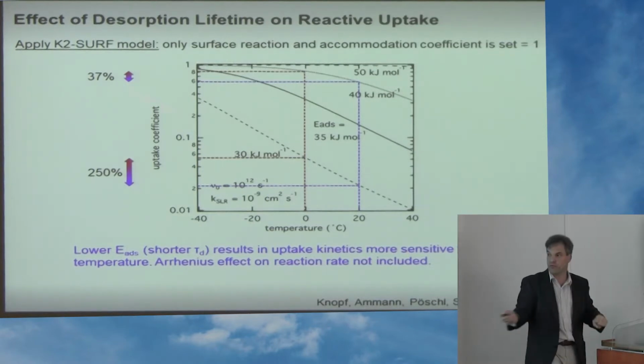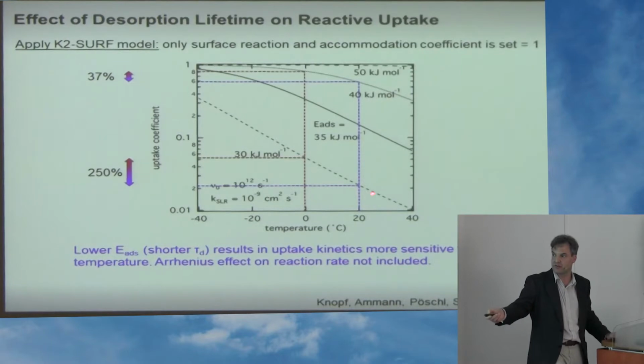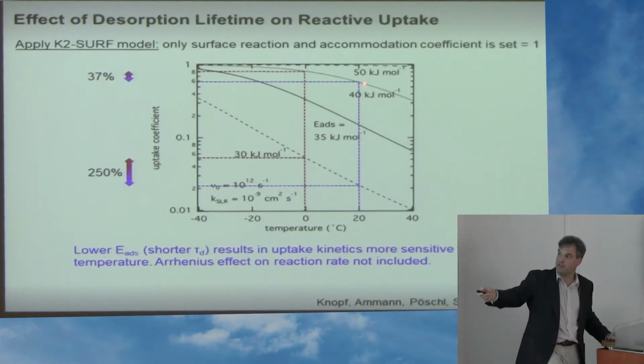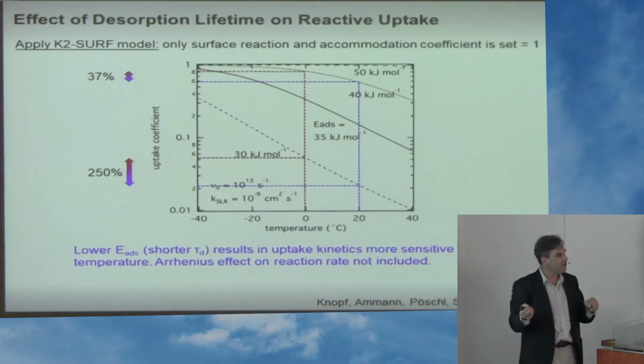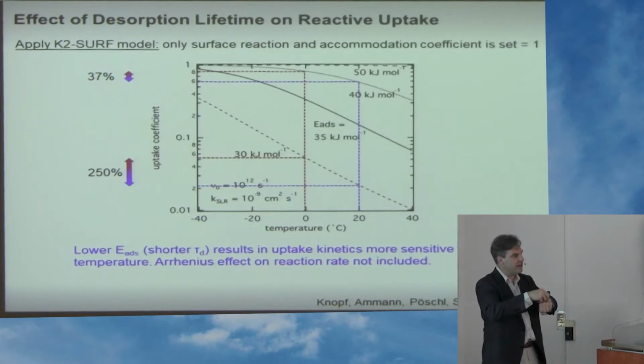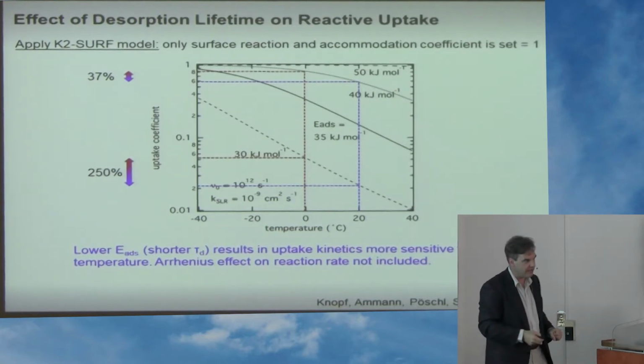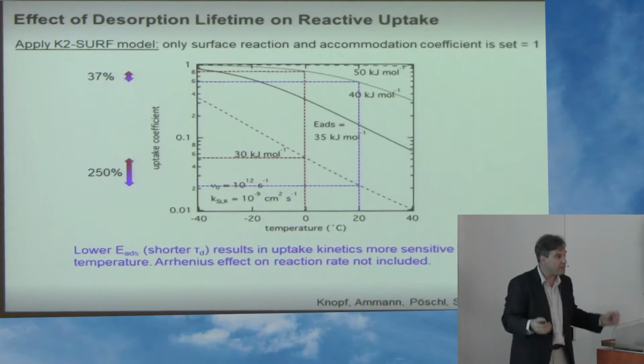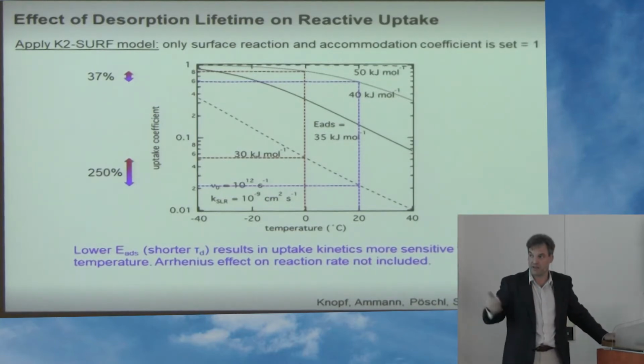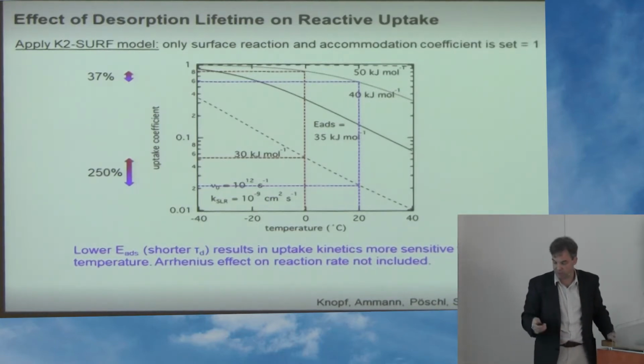And so we would completely wrongly extrapolate that in a model - in the model, we just use the room temperature measured uptake coefficients in global chemistry models. If the molecule sticks stronger due to its adsorption energy on the surface, then this effect is much smaller. So we have to know this adsorption energy and translate that into our kinetic interpretation for chemistry models, to predict the chemical evolution of that material more precisely.